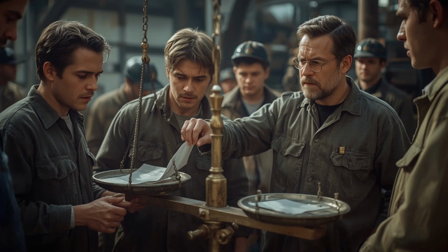But what mattered wasn't the absolute contraction. What mattered was whether different components contracted at different rates, changing the scale's geometry. The knife edge at the beam center point rested in a hardened steel groove mounted in the iron frame. If the brass beam contracted more than the iron frame, the beam might shift slightly relative to the frame. A shift measured in thousandths of an inch at the pivot point would translate to a measurable shift in the position where the platform loads were applied to the beam. This would alter the lever-arm ratio, the fundamental geometric relationship that defined the scale's accuracy.